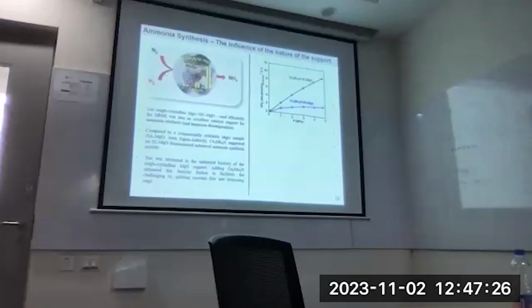Another project, we used that same magnesium oxide support for ammonia synthesis. We realized that our magnesium oxide support is slightly different from the commercially available magnesium oxide support. So I put cobalt molybdenum on it and we nitrided it using ammonia. We formed this cobalt molybdenum nitride, which is kind of an intermetallic compound. It's a very ordered compound, and it's been known for the last 20-25 years for the activation of nitrogen to ammonia.